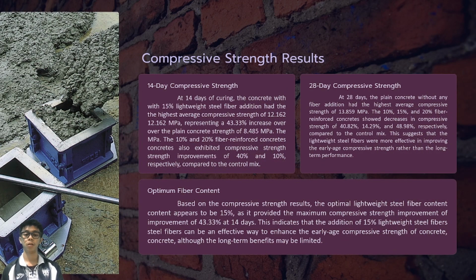Compressive strength results. 14th-day compressive strength. At 14 days of curing, the concrete with 15% lightweight steel fiber addition had the highest average compressive strength of 12.162 MPa, representing a 43.33% increase over the plain concrete strength of 8.485 MPa. The 10% and 20% fiber reinforced concrete also exhibited compressive strength improvements of 40% and 10% respectively compared to the control mix.